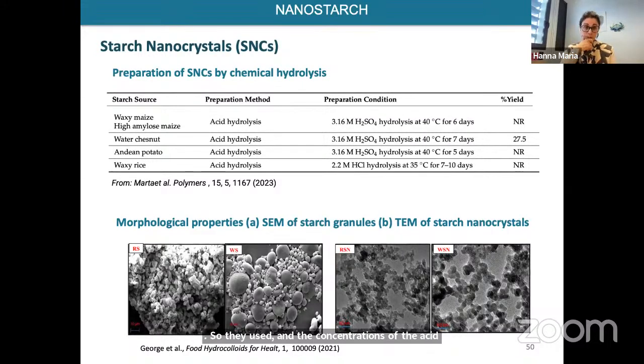They also use different temperatures, and it takes several days. Here, for instance, we have between 5 and even 10 days of acid hydrolysis. So it's really a very long process. And then you can see here two kinds of starch morphologies, rice and wheat. And you can also see the nanocrystals in the image by TEM. Okay, the different morphologies.